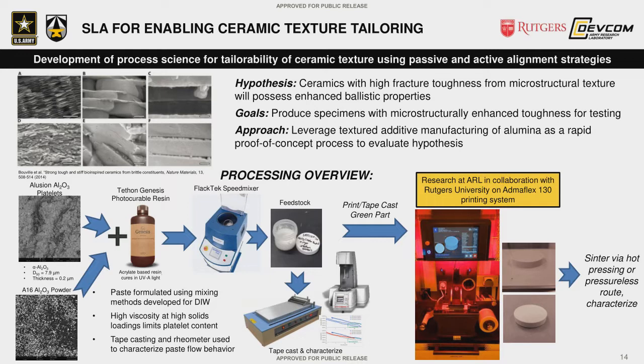So our hypothesis here is that we can create ceramics with a higher fracture toughness by introducing a microstructural texture into it, which will produce enhanced ballistic properties. And so the way we've been doing that is by leveraging the shear fields that are available in many stereolithography printing techniques in order to take a ceramic ink with these alumina platelets in it that are seeded, and shear align them during the additive manufacturing process in order to create a microstructural texture.